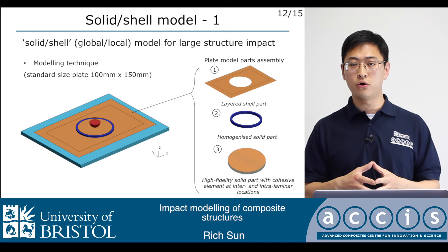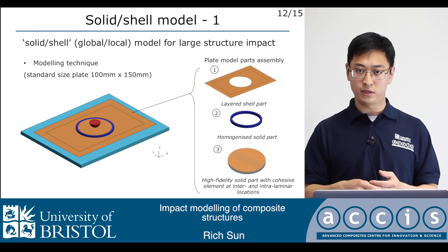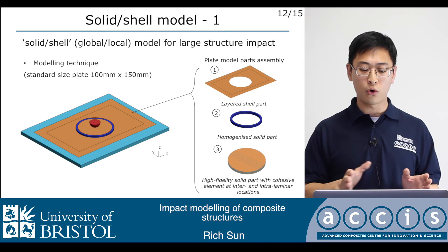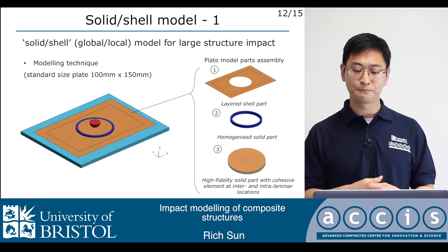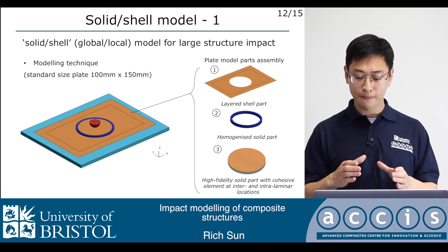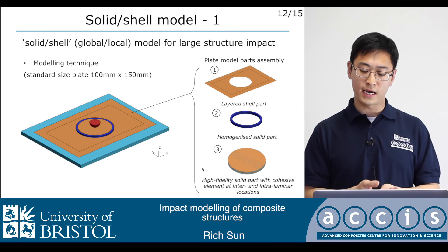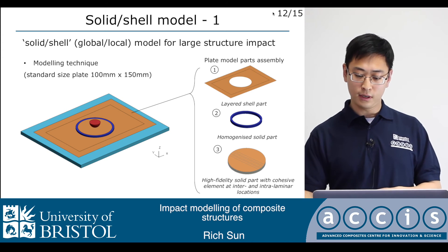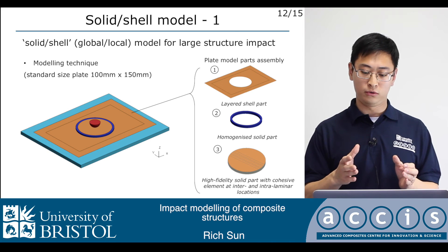The only drawback of this high fidelity model is the computational cost — as model fidelity increases, the number of elements and computation time increase significantly, making it unrealistic to deploy this full morphology for a large plate. We therefore developed a solid-shell global-local approach, reducing the high fidelity model to a circular region directly under the impact site to simulate the impact event and predict damage, while using a shell model in the surrounding region away from the area of interest where no damage is induced.